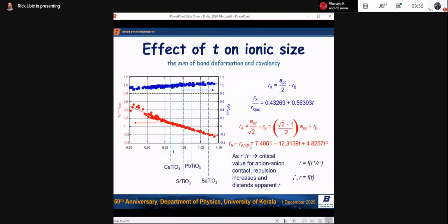So what we've done, our model starts with, first of all, R_B, the B site, is what Shannon says it is. And there's no reason to doubt that it would be. We're not adulterating the B site in any way. So the first and only assumption is that the B site behaves the way Shannon says it would. And then just from geometry, the anion size is half the lattice constant minus the B site size. That's just from geometry of a cube.